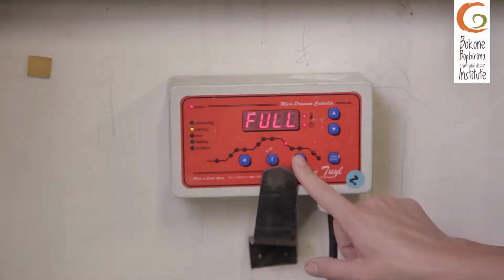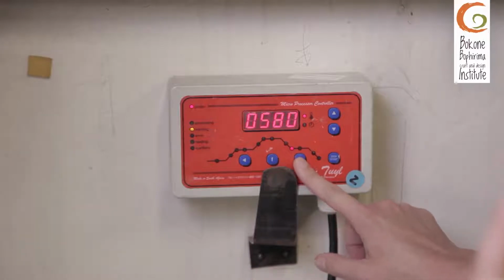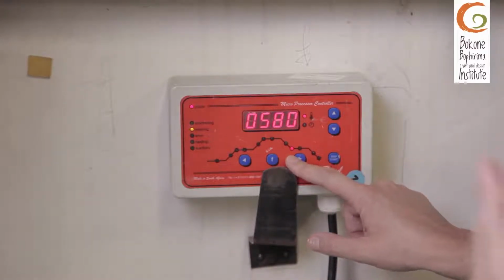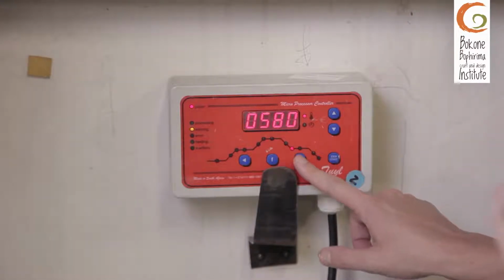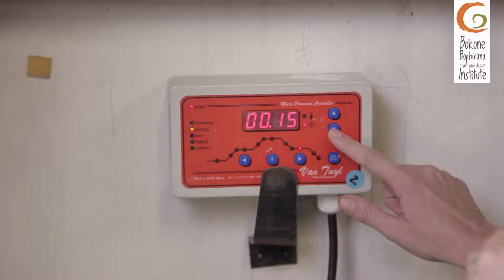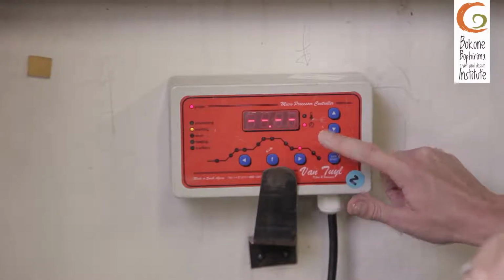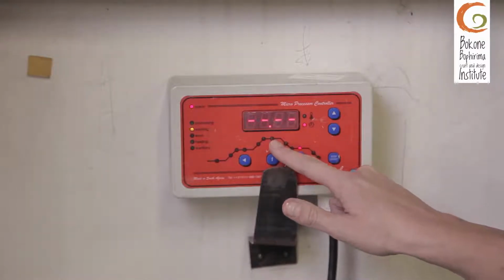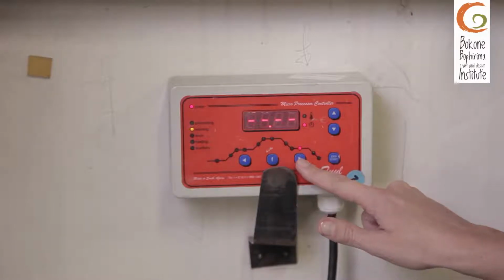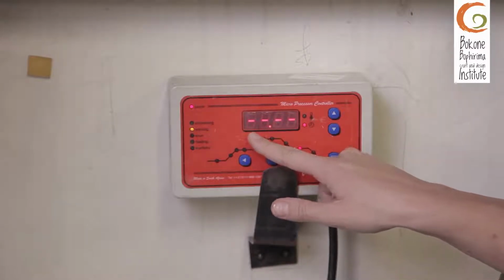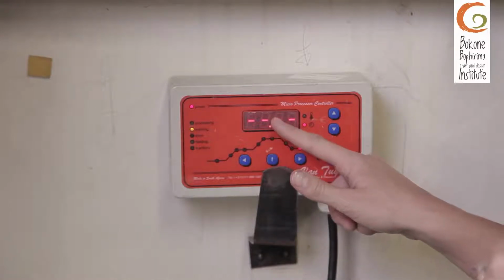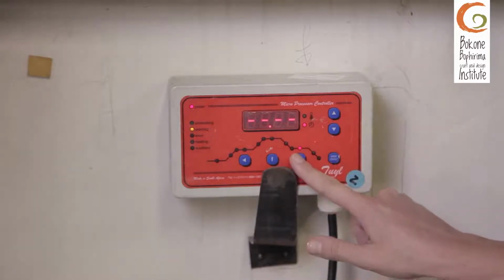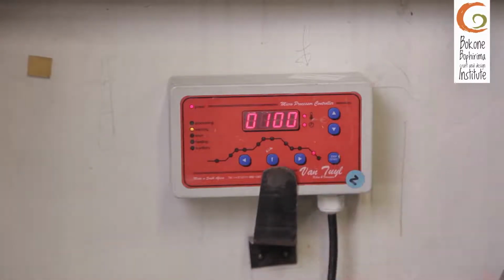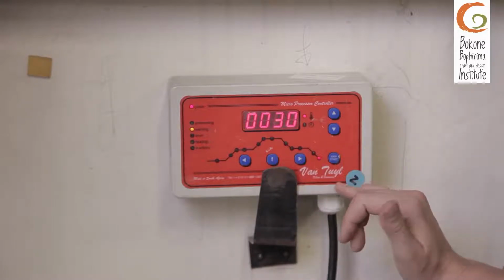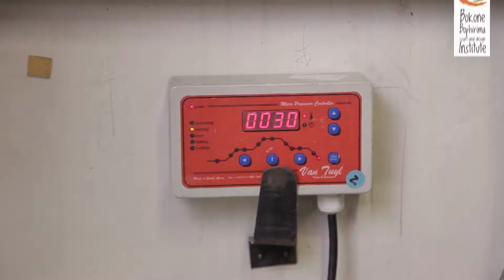So what we're going to do is we're going to say full, but we're going to cheat the system by confusing it and saying we're going back to 580. So we're initially actually just staying exactly the same temperature where we were. And because of that, we don't need to hold our process there because we're already at 580 and we held it at the top for 15 minutes. So what we're basically already doing here, we are starting the annealing process, 15 minutes at the top temperature. We are actually annealing already from the top because we have skipped that middle section there. And then we are going to put in our annealing, which I like to work with is normally 100 degrees an hour until 30 degrees, and we're allowed to open at room temperature depending on our outer environment.